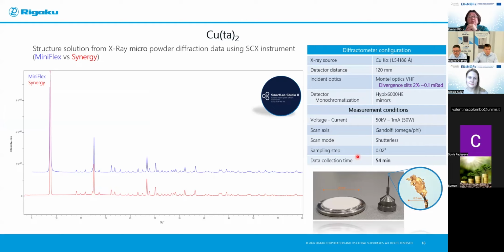This is an example measurement. It took me slightly longer, around an hour, to measure the same powder that Maciej showed you from the Miniflex benchtop instruments. The data is similar and comparable in quality, and it also allows you to use the normal SmartLab Studio workflow to solve the structure for powder. But the biggest advantage of this one is that this is micro powder diffraction.